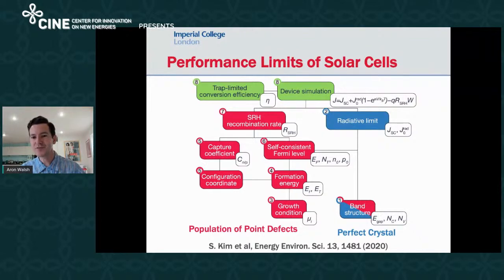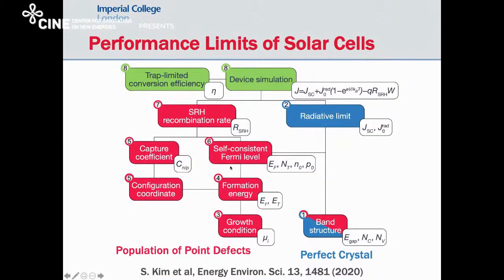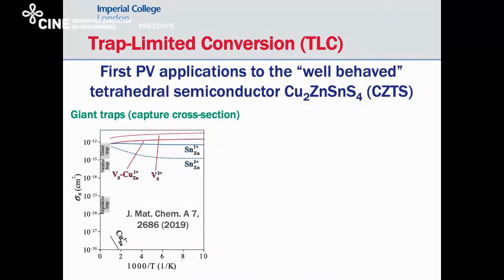So we have two strands. We think about the perfect crystal that determines radiative processes, and we think about the imperfect crystal. So what defects are present, what's the capture coefficient of each defect. We sum them up to give a non-radiative rate. Then we can combine non-radiative and radiative to come up with a metric that we refer to as trap-limited conversion efficiency. So trying to come up with something a little bit more realistic than just the Shockley-Queisser limit.